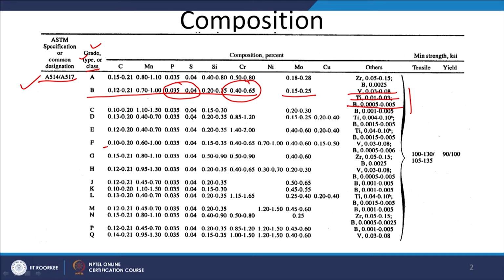So, this is one steel, and just for comparison, there is another steel, which is grade F, having carbon 0.1 to 0.2, manganese 0.6 to 1, phosphorus and sulfur both below the maximum allowed limit, silicon 0.15 to 0.35. Chromium, if we compare here, is again at the same level, 0.4 to 0.65, as that of the B grade, but this one additionally has nickel 0.7 to 1%,